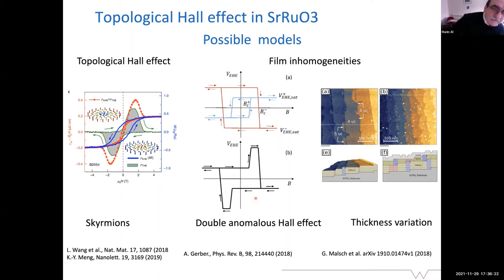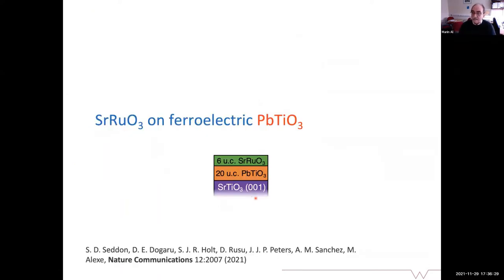It was not my intention to solve this problem, but my intention was just to have a look at what is happening with strontium ruthenate when we put it on lead titanate. So lead titanate is a very strong ferroelectric. And especially if you put it on strontium titanate, like Hongjing mentioned, you have compressive strain, and that will give a massive polarization which goes beyond 100-110 microcoulomb per square centimeter. So it's one of the greatest, along with bismuth ferrite. And on top of that, it grows very nicely on strontium titanate.